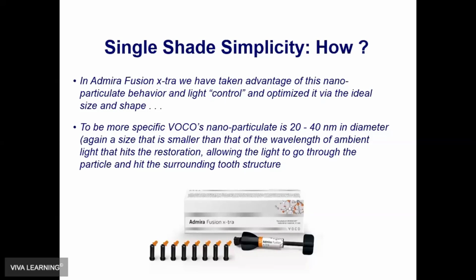Why does this happen? Why is Tokuyama's Omnichroma the same? Well, it's the shape and the size of the particulate matter inside the silicate technology that Admira Fusion Extra has. Because with 20 to 40 nanometers, what you're doing here is you are below the wavelength, a smaller wavelength than the ambient light. So the light will go through the spherical particles, not interfering with the distribution of light, the absorption, refraction, dispersion, and it's going to reflect the color of the tooth structure that you're restoring around the tooth, and it is a true chameleon material.